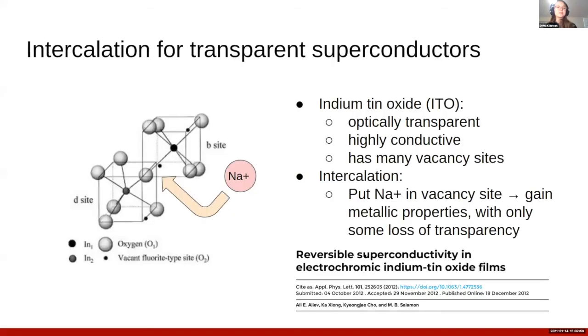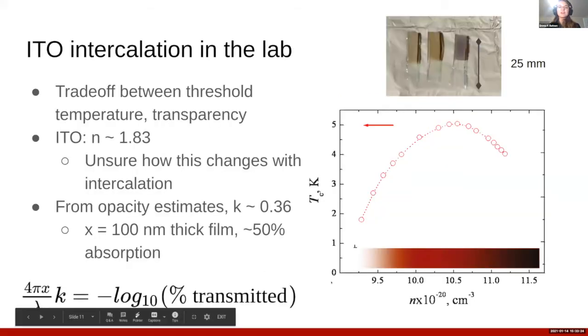There's a great paper that goes through the process of this. Basically, you can take an optically transparent, highly conductive material and intercalate it by putting something metallic, like a sodium ion, into vacancy sites in the crystalline structure. This gives the whole material, in this case, indium tin oxide, some metallic properties with only a bit of loss of transparency. There's actually a trade-off that's seen in this chart here between the threshold temperature and transparency. The threshold temperature peaks at this point where it's become pretty opaque. But if we're able to tolerate a lower threshold temperature, we can actually have something that's quite transparent.